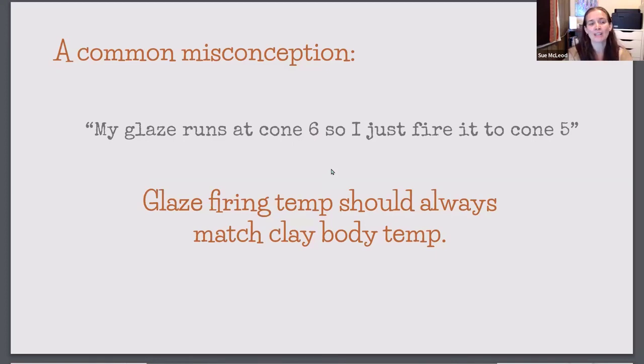So we need to not adjust the firing temperature. We need to adjust the glaze melting temperature. And that's a way better strategy. So you keep your firing temperature based on the clay body you're working with. And then you find glazes that melt at that temperature, or you adjust with the knowledge of chemistry, you adjust your glazes so that they'll melt at the vitrification temperature of your clay body.